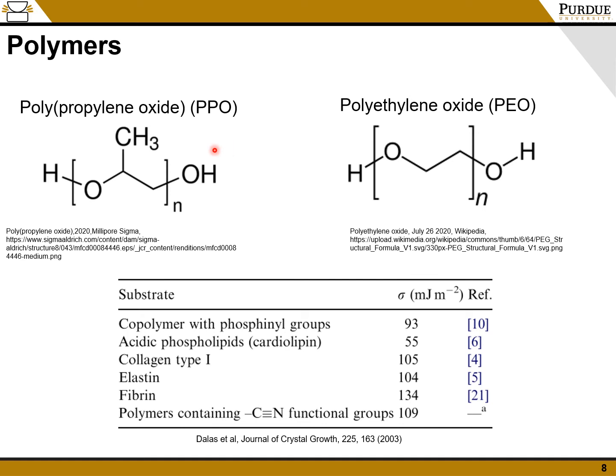In addition, they have a hydroxyl group at the ends of the polymer strands. However, this hydroxyl group, while it interacts with the salt, can also interact with the water molecules, and we don't want it to interact with the water molecules because it will pull water out of the solution and just exacerbate the phase separation problem. In addition, I saw that PEO was more effective at starting nucleation crystals than PPO because